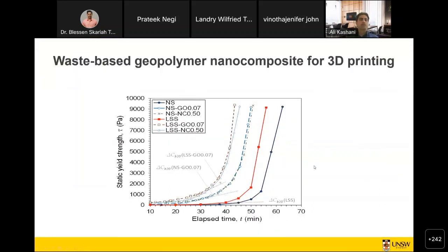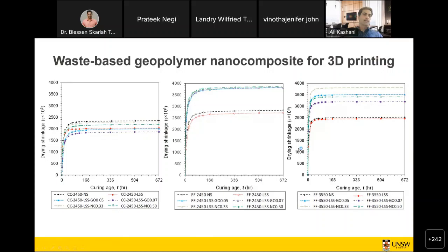Okay, so again, apologies. I was talking about how we use the nanoclay and graphene oxide to get better strength buildup that we need in terms of the buildability of the geopolymers, as you can see in this graph. In terms of drying shrinkage, using graphene oxide helps with reducing the dry shrinkage in normal curing condition, opposite of the nanoclay because of extra water absorption between layers of the nanoclay. And also, as you can see, using the lead smelter slag, the red lines here, also helps reduce the dry shrinkage compared to normal.